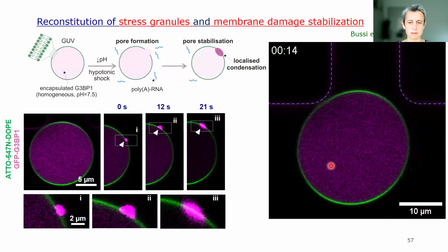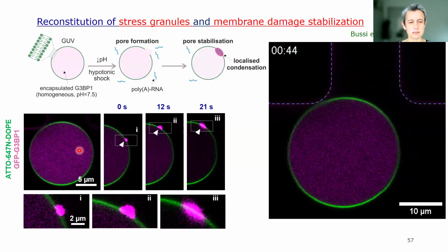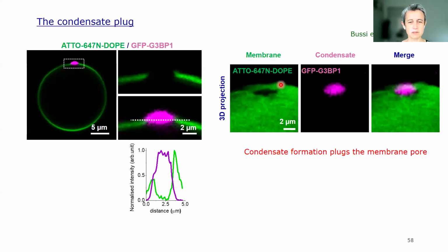And this is indeed what happened. This movie is a little bit more complex, but over time, one sees that after poration, the condensate forms, and then if you do some imaging of that, you see the pore in the membrane that is plugged by the condensate.